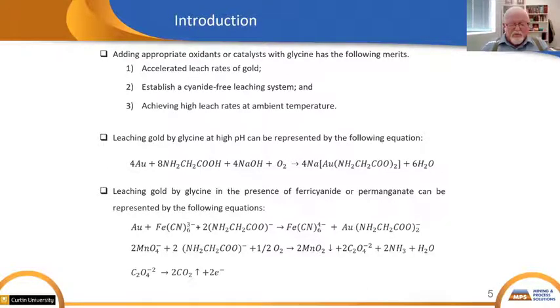Glycine on its own can leach gold very slowly, but at high temperatures and high pH, it can become very aggressive. And under certain conditions, potassium ferricyanide, potassium permanganate, can aggressively oxidize gold and make it available to be complexed by glycine.